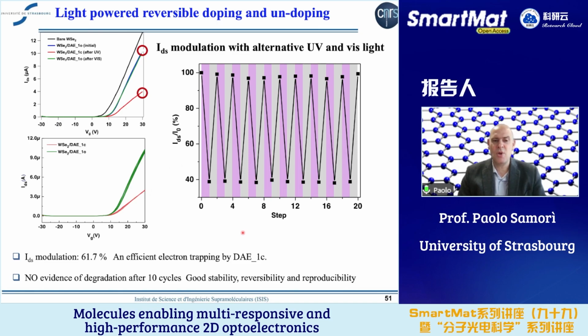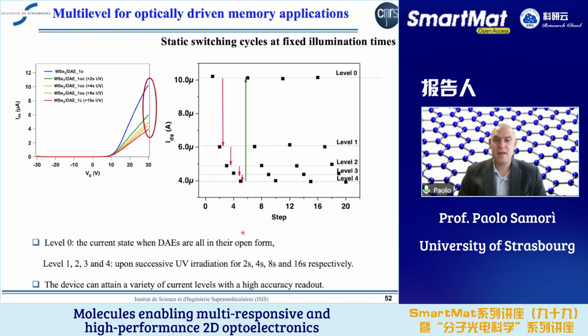modulate the current through a junction by 60% with an efficient trapping and detrapping of the electron. So we see a high robustness of our switching, so high reversibility and no degradation. Now, of course, we can try this to be used for memory applications. And so the idea in this very preliminary study was to start from the open state where the current is the highest. And then we irradiate with UV light for 2, 4, and 8 seconds.